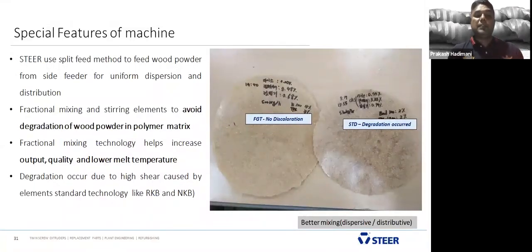Later, we took two samples separately and put them in a compression molding machine. If you see the left-hand side, the FGT technology sheet, we didn't observe any black specks, and it looked like natural fiber. But with the standard technology, we observed black specks and degraded colors. It is due to the high shear. Due to the high shear, the wood powder started degrading. If you use fractional geometry technology, it reduces the melt temperature, and with lower shear rate throughout the system there is no degradation of wood powder in the FGT, but we observed degradation in the standard technology.